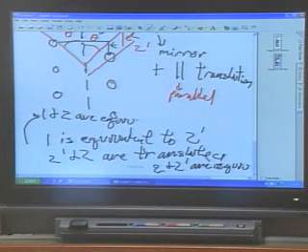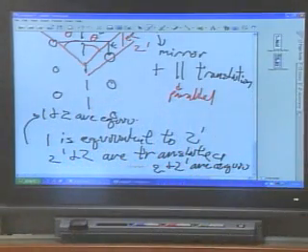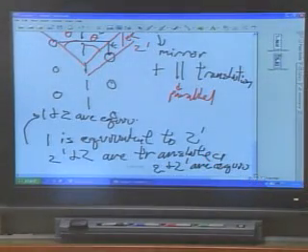So this is why, in some sense, it doesn't matter whether or not you have a symmetry element which has a translation or doesn't have a translation with respect to any of the properties. If you're concerned about the symmetry of the properties, that is, whether or not the property will be the same if you mirror across or you do any type of rotation operation, all you need to know is the point group symmetry. You don't really need to be concerned about any translation.